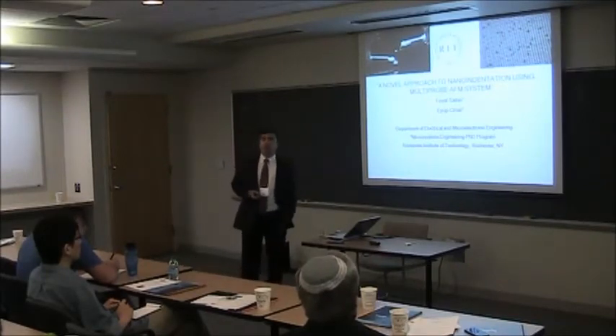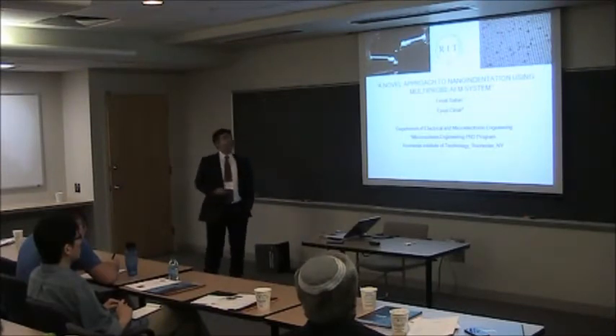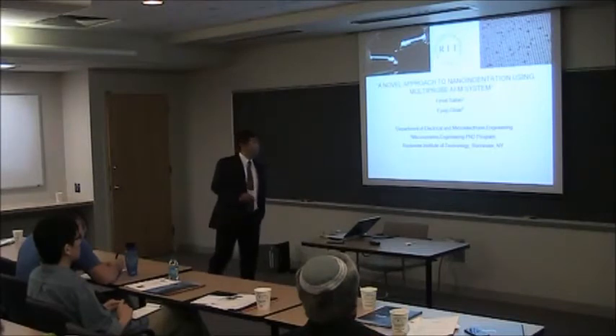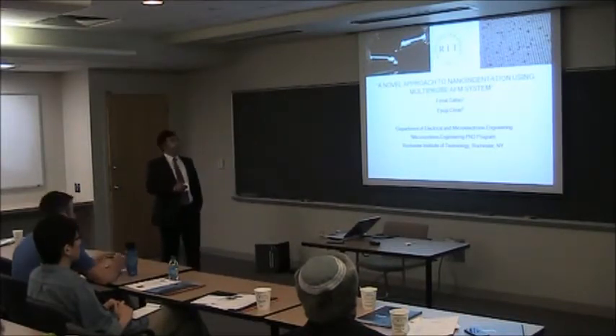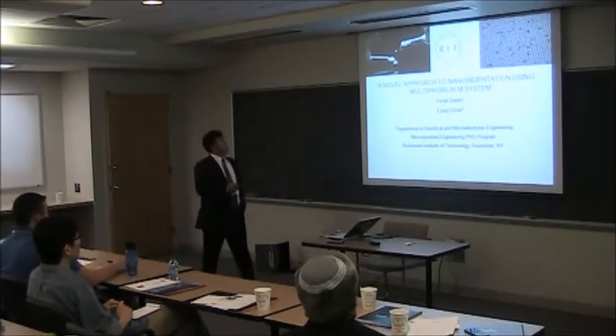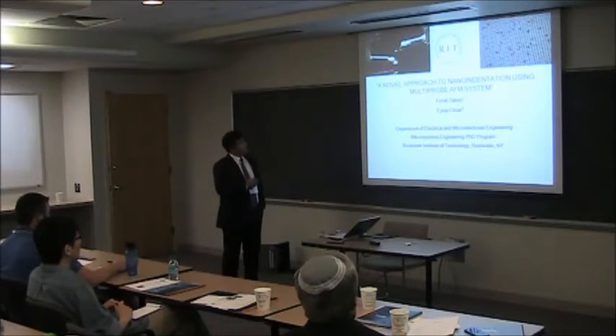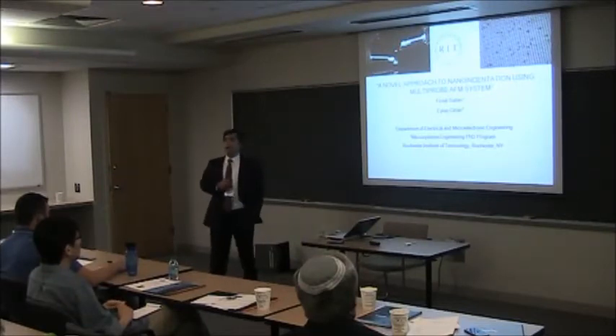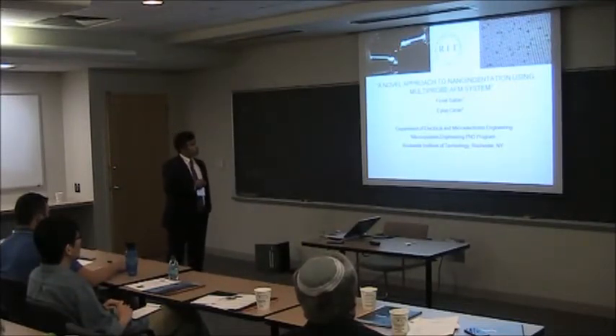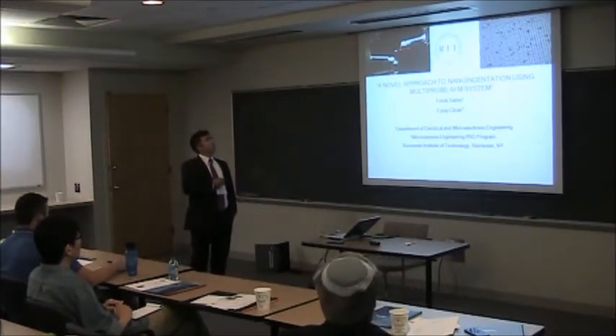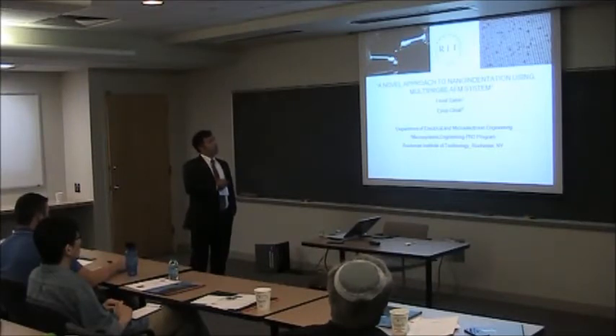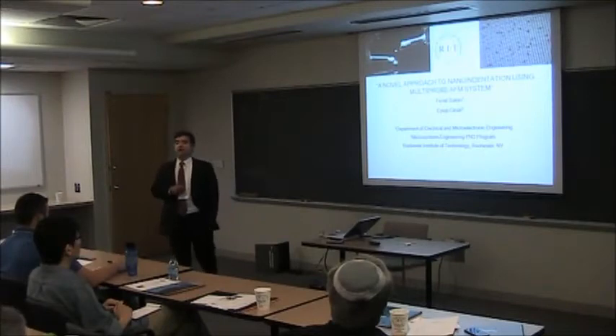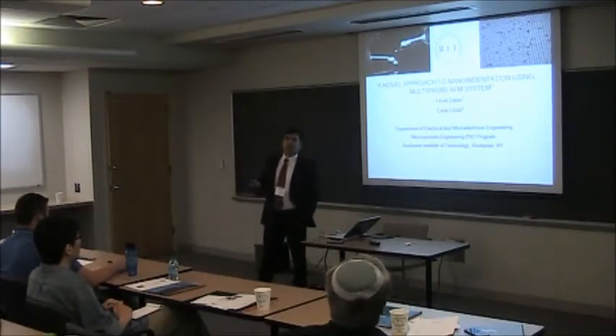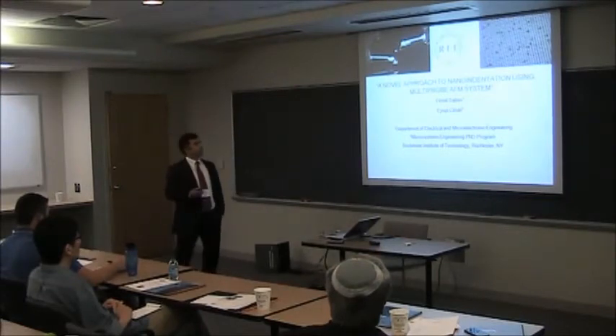So that was the starting point for us to actually go into PDMS and go into how we can actually quantify that force. On the left is the multiprobe system we have. We have Multiview 4000. On the left, there is a tuning fork with a diamond indenter attached. And on the right, another probe which has a regular AFM probe. The probe is touching the top of the diamond. And what we do is we move this diamond down and indent. And then while this is fixed, we move the stage up and try to measure any change of the diamond, so that we can actually have the X change or Z change, but in the force calculation, X change.